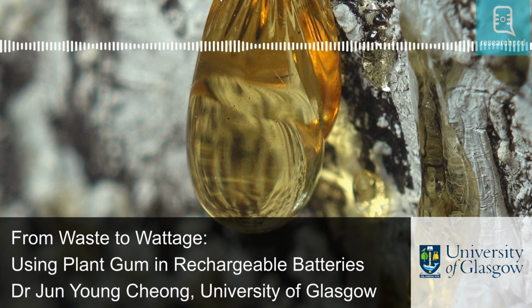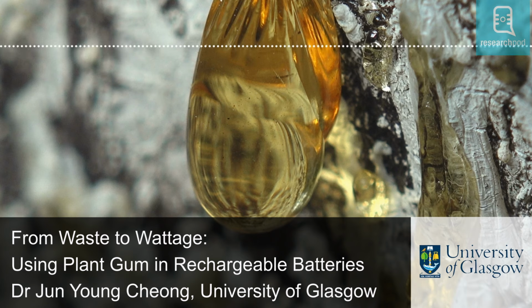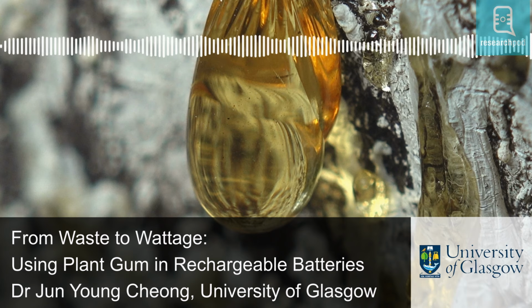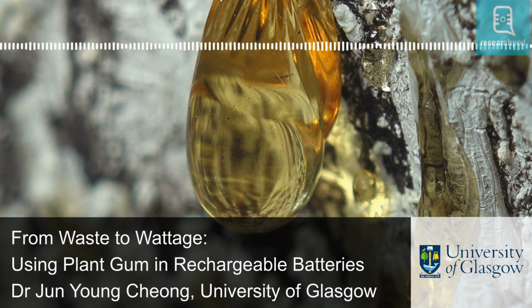Researchers finally tested the stability of each anode build. After 200 cycles of discharge and recharge, the traditional anode experienced capacity degradation. This means the unit could not store or produce the same amount of electrical energy as it could previously manage. Meanwhile, the water-soluble binder based anode maintained a higher capacity for up to 360 cycles.